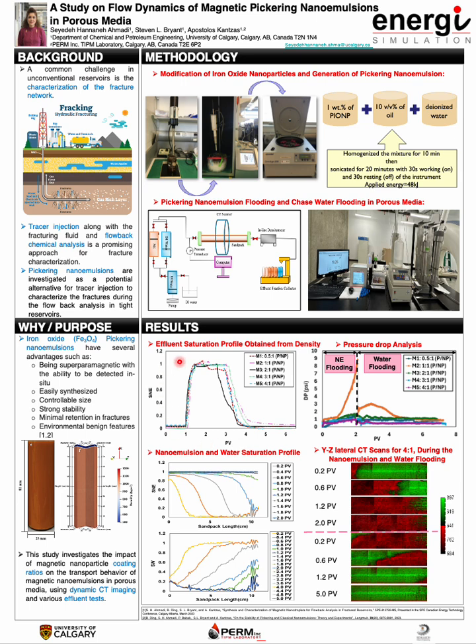And here in the results part, you can see some results from the experiment. First of all, you can see the effluent saturation profile obtained from density. We use the density of effluent, density of nanoemulsion, and density of water to normalize the effluent density and draw this graph, and it demonstrates how the nanoemulsion saturation profile develops as a function of injected pore volume during this flooding process.